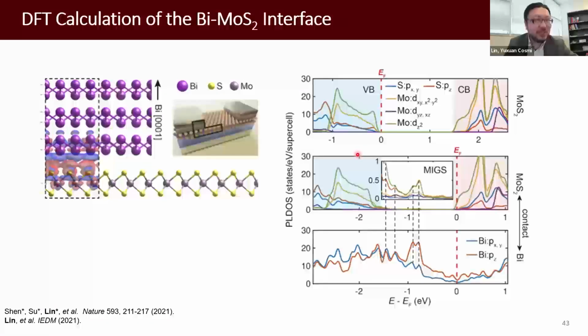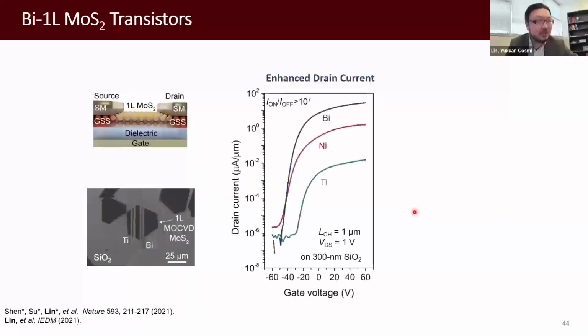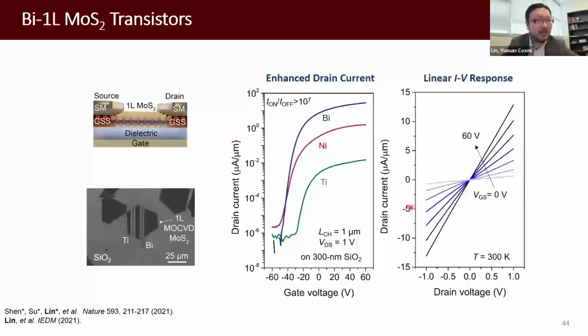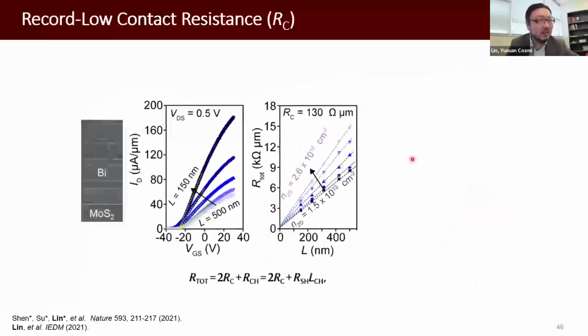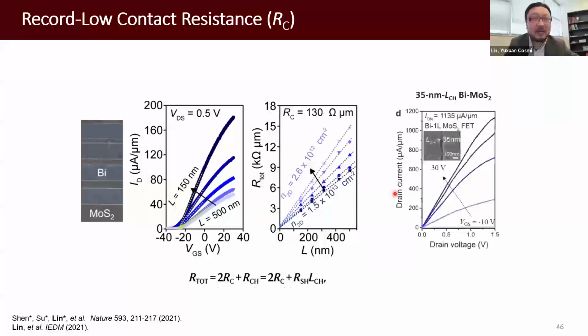So we explore this bismuth from theoretical calculation. We indeed see these MIGS states within the band gap. They are super weak. And we also fabricated devices to demonstrate that with the bismuth contact, the device performance can be much better. We use this TLM measurement to extract the contact resistance. It's about 130 ohm micrometer. That was the best at that time.